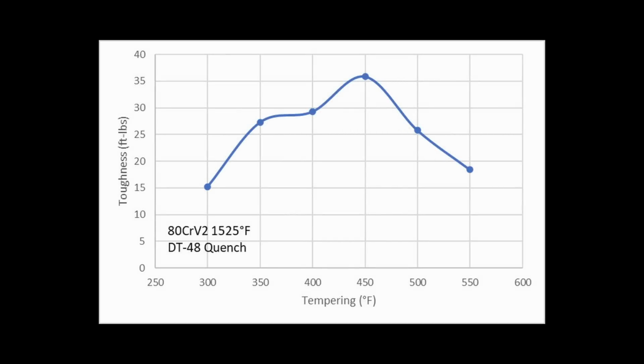Also, some steels don't see tempered martensite embrittlement until higher temperatures, like 80CrV2 and 26C3. Both of them you could temper all the way up to 500 degrees, 450 degrees, and they were still tough. And it wasn't until you tempered hotter that they would see the drop from tempered martensite embrittlement.